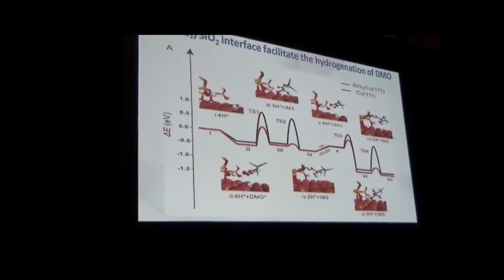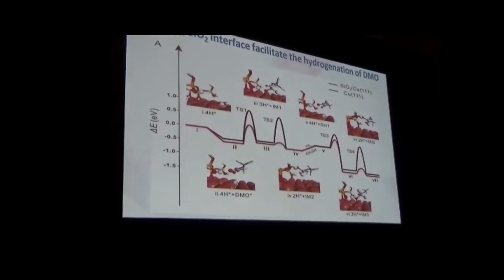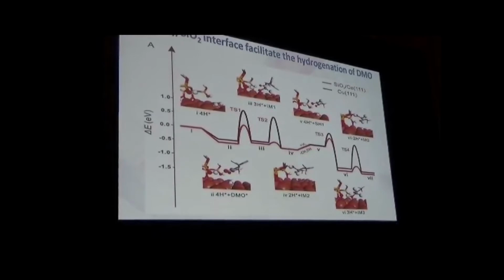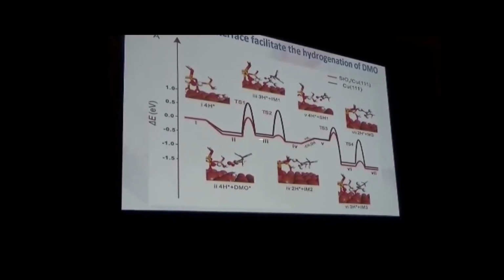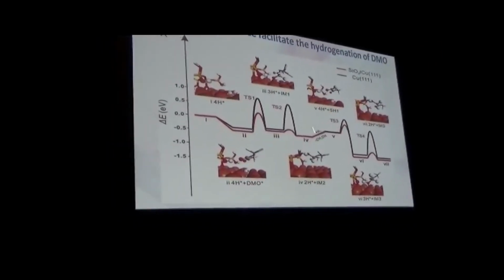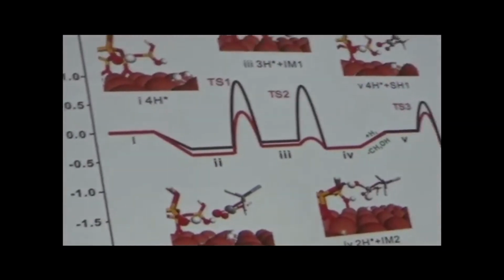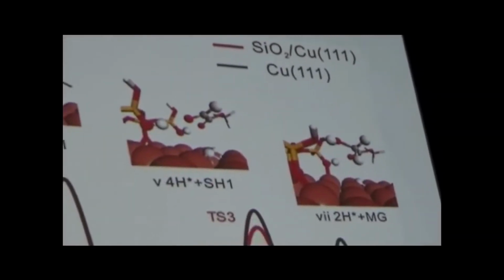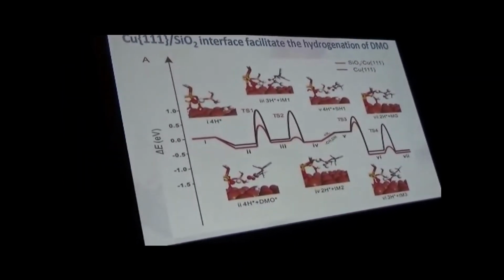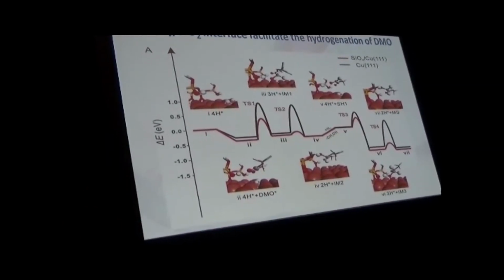We have calculated the full hydrogenation process for the one ester group. Here you can see that the black curve is on the copper surface, and the red one is for the silica copper interface. You can see that from the thermodynamic view it is nearly the same, but from the kinetic view, the interface system can stabilize the transition state rather than the intermediate.